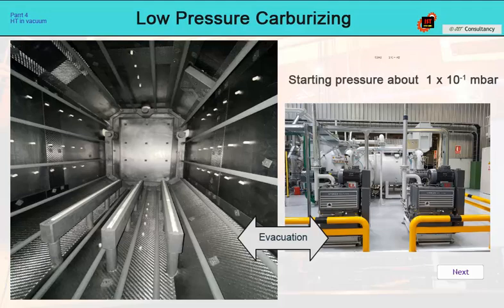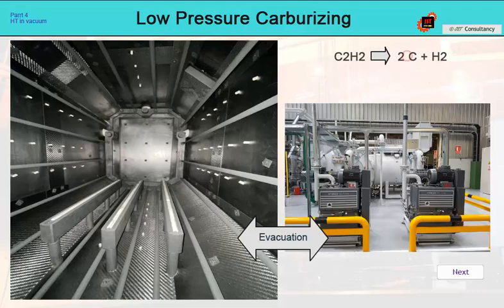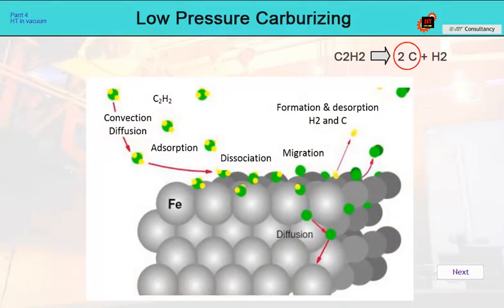Once it is reached, carburizing gas begins to be introduced into the furnace. If the carburizing gas acetylene comes into contact with the high temperature of the surface of metal parts, its catalytic dissociation occurs. The acetylene releases atomic carbon, which is capable of diffusion. The remaining hydrogen is sucked away by the vacuum furnace pumping system. However, once the carbon penetrates the steel surface, the next process is the same as in classical carburizing, governed only